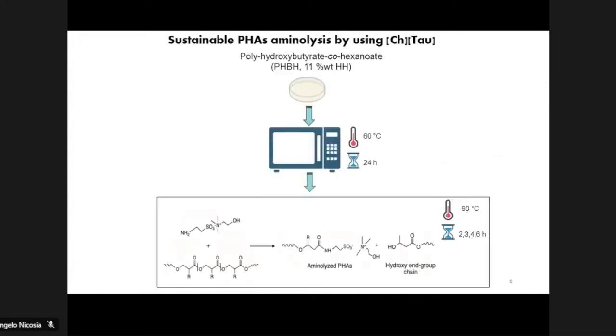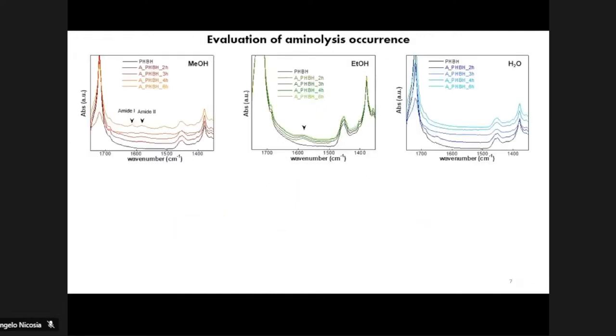Cast films of polyhydroxybutyrate-co-hexanoate were first of all thermally annealed and then aminolyzed at 60 degrees for different contact times in the selected solvents. Spectroscopic characterization highlighted that alcoholic solvents are good solvents for aminolysis since the typical amide peaks are clearly visible, while no changes are detected when water is used as a solvent.